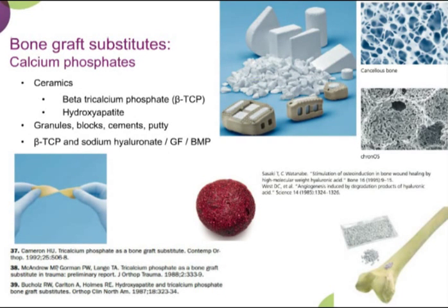Hydroxyapatite is actually much less used because it's considered to be a more brittle substance and it has a very slow in vivo resorption rate. But it's thought that HA may actually have a slightly greater osteoinductive effect, and it's synthetic HA.